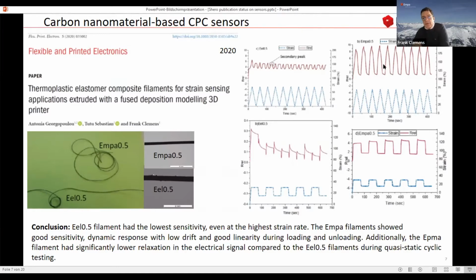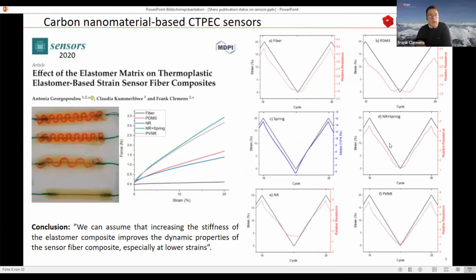And here, for example, you can see a sensor which we developed by ourselves, and you can see that nicely we can follow the strain signal, as well as you can see that even when we apply this quasi-static experiment, we can get a very good and stable sensor signal. So the other thing was then that we wanted to know, okay, what's happening if we put that now into the matrix? Because this is at the end the idea.